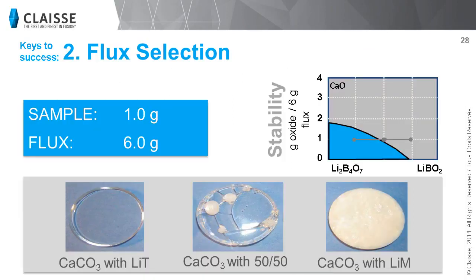In this second example, we repeat the same experiment but using a sample made of pure calcium oxide. Once again, the only thing that has changed is the type of flux. In the first disc on the left, we use lithium tetraborate to fuse the sample. You can see that we have obtained a perfect disc that is ready to be analyzed.